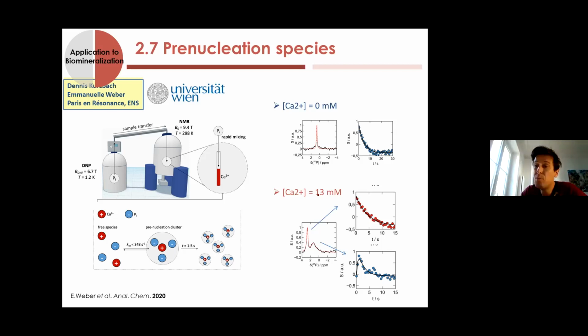So I would say that the limiting factor is the relaxation, and the relaxation also depends on the field that you are using. So it's not so obvious, but I would say that in our case, when you are dealing with species that are around 1 nanometer, it's okay, 1 or 2. Now at 10, it's starting to be difficult, and at 100, it's over.